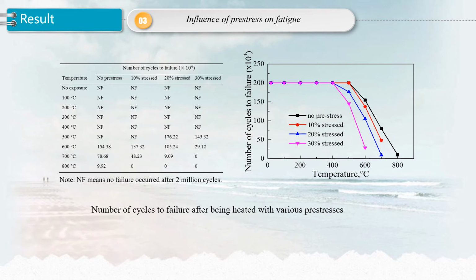This picture shows the number of cycles to failure after being heated with various pre-stress. It can be concluded that pre-stress can significantly reduce the fatigue resistance. Under 400 degrees centigrade, all wires were able to resist 2 million fatigue cycles. However, beyond 400 degrees centigrade, the number of cycles to failure with initial stress dropped significantly as temperature increased.